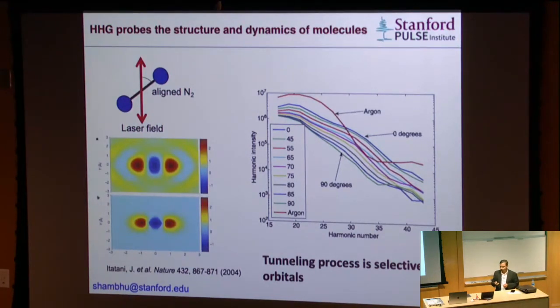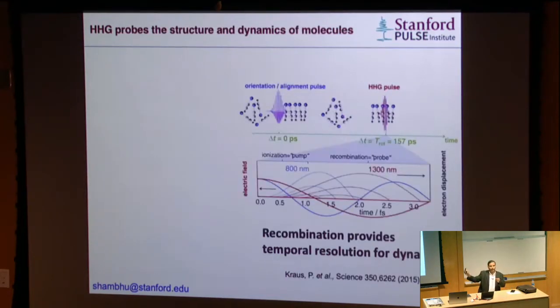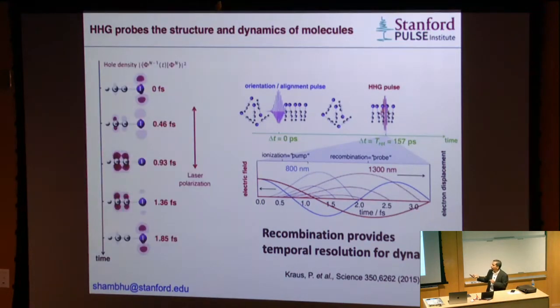These are the HOMO orbitals, right? And on this process of when it is coming back, right? If anything happened to the target itself, if there was some interesting dynamics going on in the target itself, because for example, in some bigger molecules, there could be some interesting dynamics. You also can probe what happened in that molecule, because you can so precisely control the time at which the electron would come back and recollide. Okay, because you have the knob of the laser wavelength, for example, as shown here. And when they did this, they were able to actually experimentally probe on this molecule how the hole density was moving from one side of the molecule, like here, to the other side, and then coming back in a really fast, femtosecond time scale.